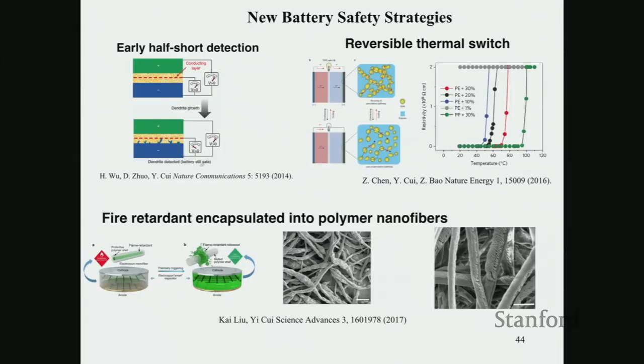If you have a shorting happening in one of these current collectors, we have a polymer layer with a nano spike of nickel embedded inside. At room temperature, it's conducting. But if your battery heats up to high temperature, this polymer volume expands and pulls the nickel nano spikes apart, so a lot of these particles open. So the whole layer becomes an insulator. That makes the release of the electricity very hard, so you don't heat up your battery that much. You have a thermal switching that can be controlled to close to 100 degrees Celsius, and the electroconductivity goes from metallic to insulator at a controlled temperature.